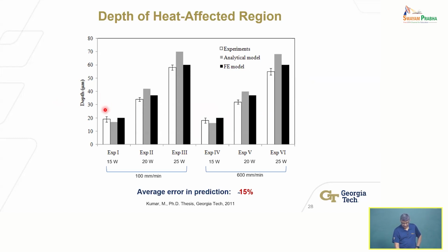So here is a comparison of using the analytical model, the experiments, and the finite element model. The depth of that affected region, I showed you a picture, 30 microns, in this case changes when you're varying the laser power, right? So here the laser power is increasing for one speed. This is slow scanning speed. And the next one is the same laser powers, same trend, but for a higher scanning speed, okay? And in general, at a higher scanning speed, you can see the depth is a little less, right?